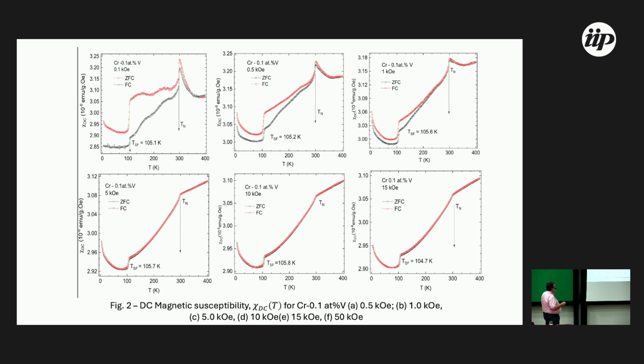When performing field cooling, we observe the big jump in spin flip, but it is a small field, 100 Oersted. When increasing the magnetic field, for example, to 1 kOe, the Curie-Weiss behavior starts to disappear. At 5 kOe, it is the same behavior as chromium, Pauli paramagnetism here. Okay? And the increase in spin flip. The spin flip temperature depends on the applied magnetic field. The dependence in this sample is very small.